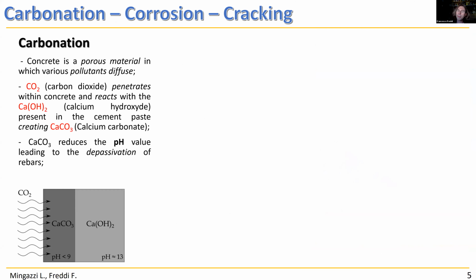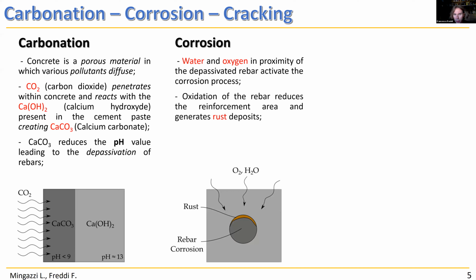Let's move to physics. The main aspect of the problem, first of all, is carbonation, because concrete is a porous material where many pollutants diffuse, but for the case at hand, the most important is the carbon dioxide that reacts with the calcium hydroxide, and calcium carbonate is created. Apart from secondary effects, the calcium carbonate reduces the pH value, and this leads to a depassivation of the rebar. If water and oxygen are present in the neighborhood of the bar, the corrosion process starts. And there is an oxidation of the rebar.